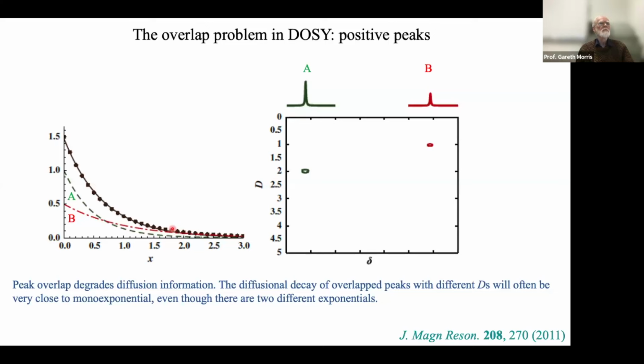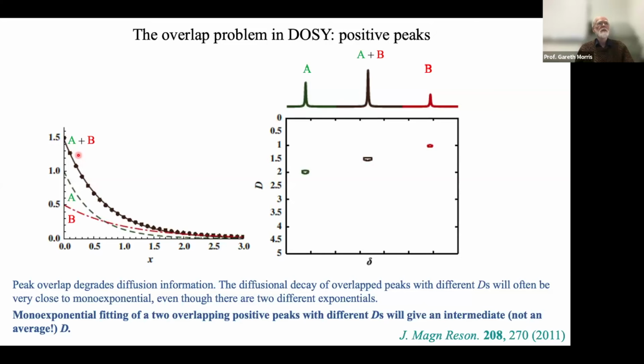Let's do DOSY processing. Sure enough, what we see is that these data are really very well represented by a mono exponential, even though we know that they're two different exponentials with decay constants that differ by a factor of 2. And you might think, surely in our statistical process, we should get a warning. We should see that the estimated uncertainty is increased because we have different overlapping exponentials. In practice, we don't see very much increase until our diffusion coefficients are very different.